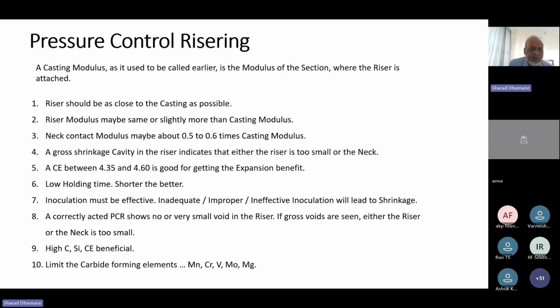Okay, so some basic points. Riser should be as close to the casting as possible. Riser modulus may be same or slightly more than casting modulus. This is relevant to ductile iron, not relevant to steel or aluminum bronze or copper alloys. Strictly, they want riser modulus to be 1.2 times casting modulus.